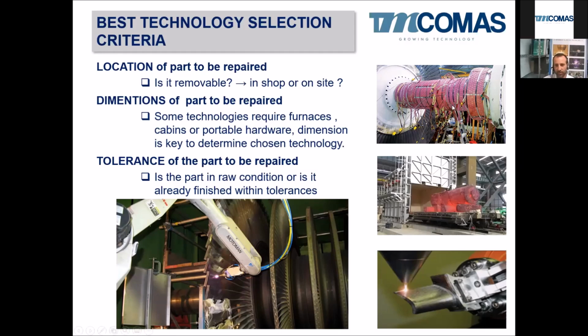It's clear in this example: here we have a very big turbine, and someone is performing a heat treatment on site, clearly with all these thermal blankets to control the temperature and the heat treatment on this area. On the other hand, for example, in this big ingot, we have enough space in an oven, or the part is not finished, or the part can be moved to that big oven to make the heat treatment. So the dimensions are quite important as a criterion.